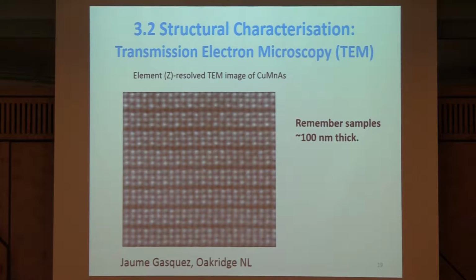So you're looking down at these columns of atoms, one above the other. So if, for instance, there was quite a high density of point defects in there, you might not see it in this. If 1% of the atoms were missing, it would probably look pretty much the same, unless those led to more extended defects.